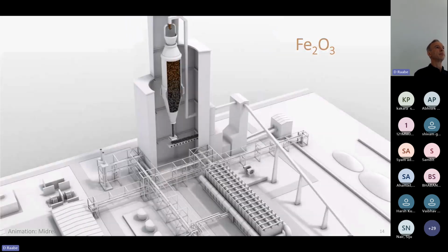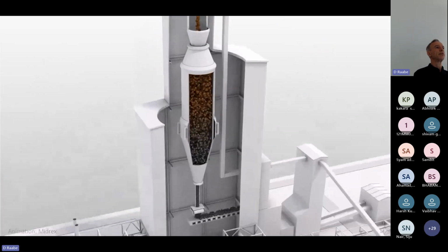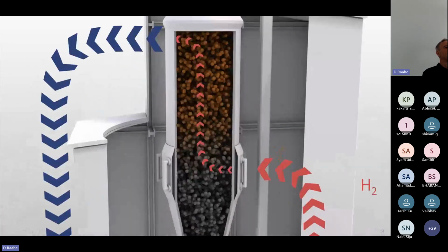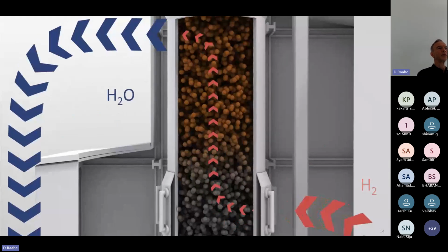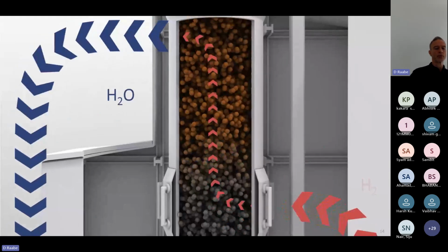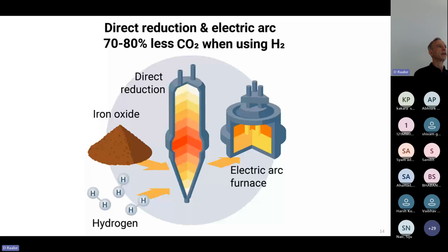So you have a counter-stream shaft reactor, which is currently fed by steam reforming, of course, but you can do that also, as you know, with pure hot hydrogen, and the redox product would then be water. And the overall schematical principle of what you do with that reduction product, namely the so-called porous iron sponge, is shown here. You feed it maybe together with scrap into an electric arc furnace and bring it then to the downstream metallurgy.